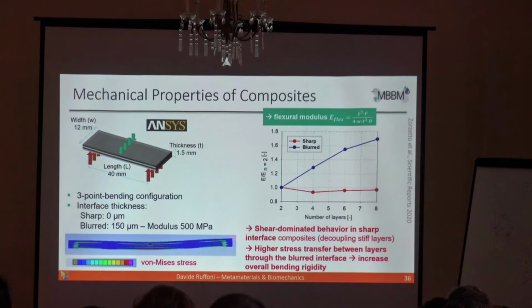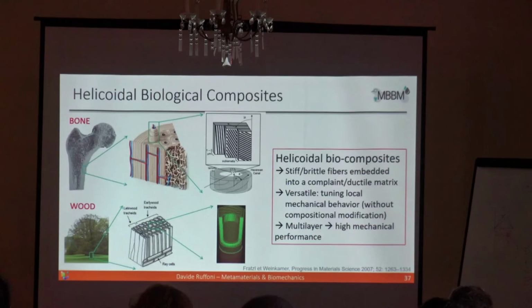And if you have a blurred interface, knowing that this blurred interface has properties more similar to the stiff material, well, it allows a higher stress transmission between the layers, and of course it allows the behavior to be more in line with the prediction of beam theory. So this is what was our, let's say, study to characterize interfaces.